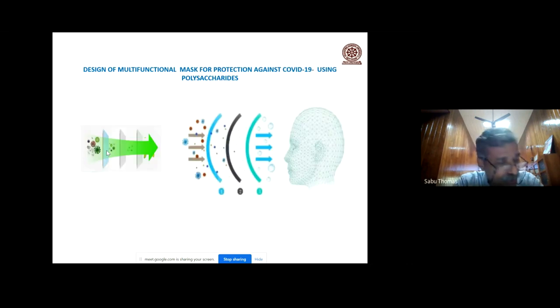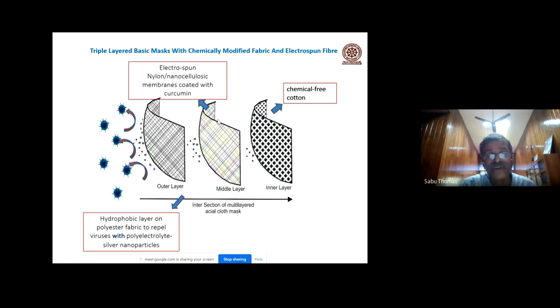Let me show you another interesting work. During the COVID time, dear friends, we proposed the India-US program on the manufacturing of a tri-layer mask. The outer layer is made of a biodegradable polyester coated with an anti-adhesive layer. The middle layer is made of biodegradable polyamide coated with curcumin and nanocellulose. And the innermost layer is made of cotton. When the coronavirus comes in, the outer layer has an anti-adhesive coating. It can repel the coronavirus. And the middle layer is made of electrospun nylon coated with curcumin and nanocellulose, which is positively charged. So it can kill the coronavirus, if at all some virus gets into it. So this is the configuration we have made.